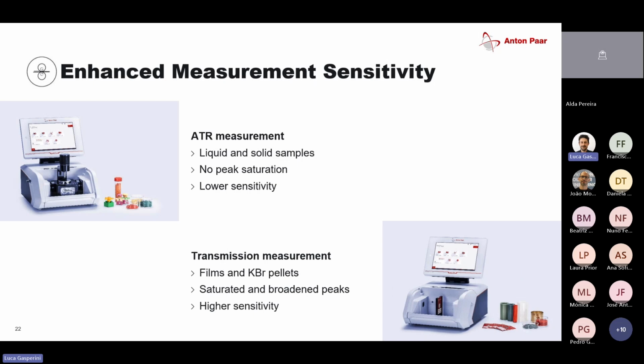So in this case, you either press a film or you have KBr pellets. For the people a little bit more experienced, 20, 30 years ago, you were using KBr pellets for samples which absorb not enough. So what you did is you had KBr powder, and then you took a little bit of the sample, mixed it, and got a KBr pellet like this, and then you measured in transmission. This was before ATR time.